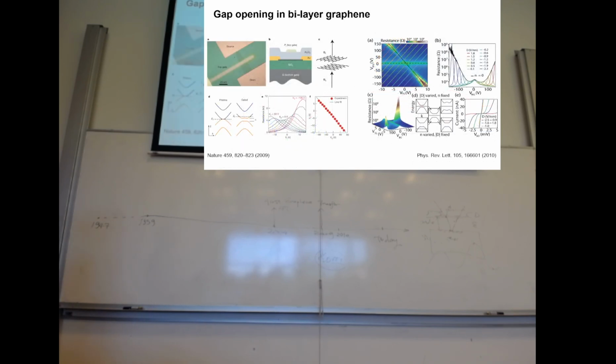And let's come back to this question of bilayer graphene again. You can see that if you apply a vertical electrical field, you can create a little band crossing between the conduction and valence bands. They overlap, and a avoided crossing forms this so-called Mexican hat structure. And you have very high resistance peaks at different gate voltages. To create a vertical electrical field, you need 2 gates, a top gate and a bottom gate. That's how you scan this graphene resistance in the parameter space of bottom gate and top gate.